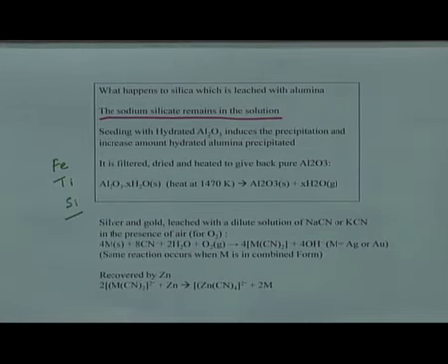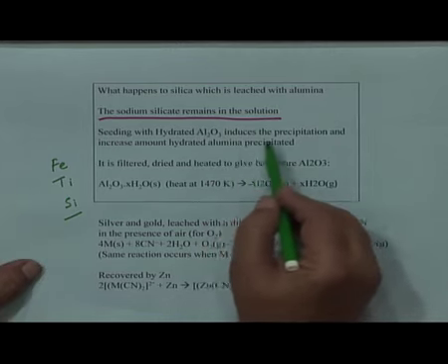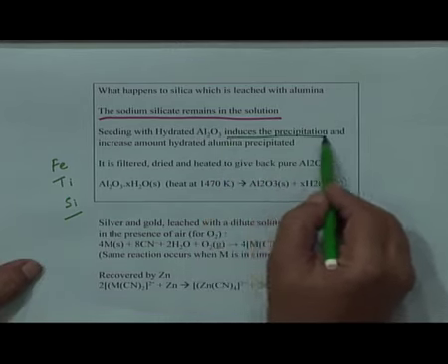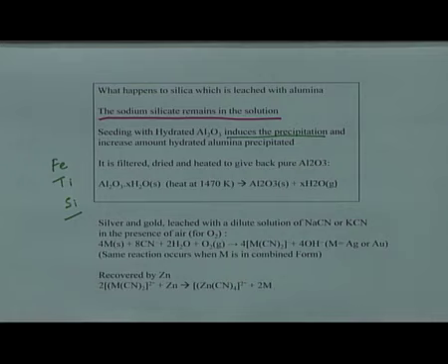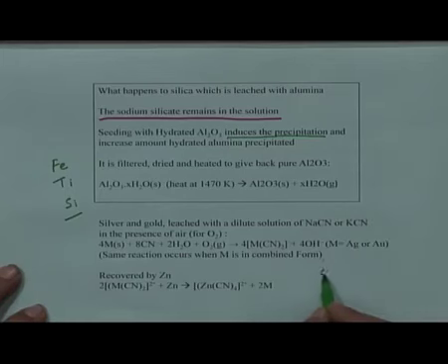Now, it is possible sometimes that alumina does not immediately precipitate. In such a situation, we induce the precipitation. For inducing precipitation, a small amount of hydrated alumina is added to the solution, from which it is coming out very slowly. This added alumina acts as a center of crystallization.